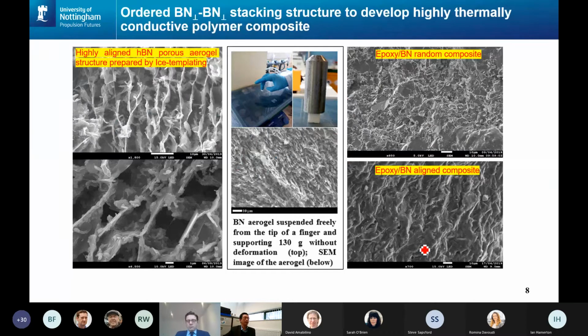These structures, we call it aerogel. After certain treatment, we can get this very porous aerogel structure. You can see here the alignment of boron nitride platelets. Here is an enlarged image along these directions.